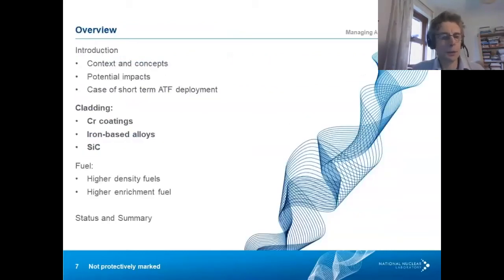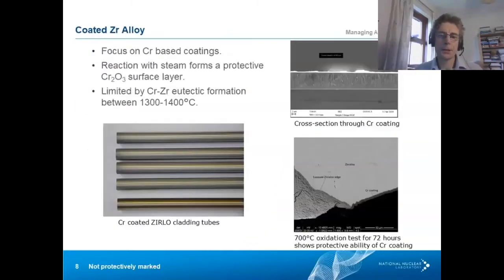So moving on to have a closer look at the claddings now. The first cladding and the most advanced options are associated with coating the zirconium alloy with a non-reactive coating, of which chromium has been the most attractive option and the one which is furthest towards deployment. In these, chromium is deposited as a very thin layer on top of the zirconium cladding. It provides a non-reactive surface which produces a chromium oxide (Cr2O3) surface layer, which continues to protect the cladding up to much higher temperatures and delays the onset of any zirconium steam reaction.